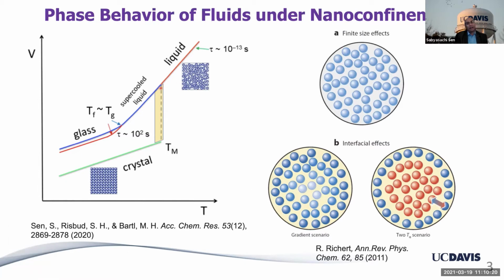And that transformation can happen over a narrow range of temperature because first order transitions are driven by nucleation and growth often. And so the crystal nuclei, for example, need to grow in the liquid. So over a certain temperature range, crystal and liquid can coexist. But eventually, below the melting point, the liquid turns all into crystal in that kind of a phase transformation that we all know in the bulk state. What I'll show you is that that may not be necessarily true, and crystals and liquids can stay together practically forever or for a very, very long time when you keep them confined in nanospaces.